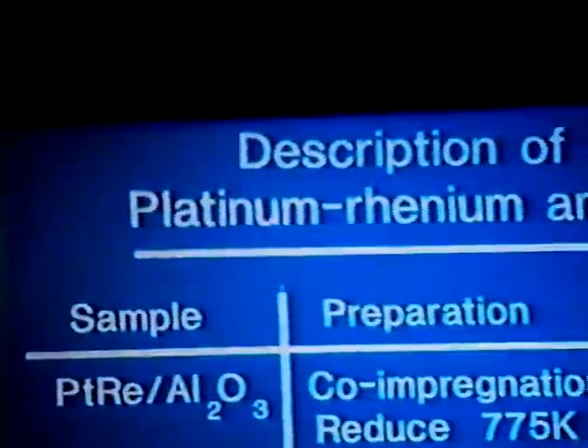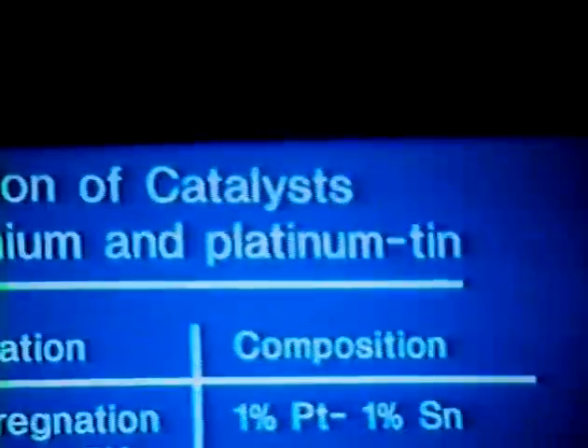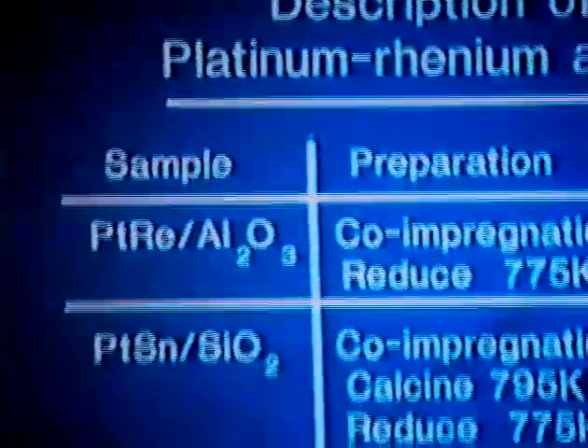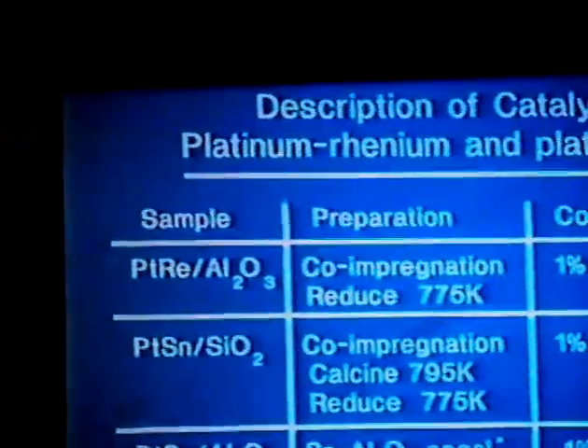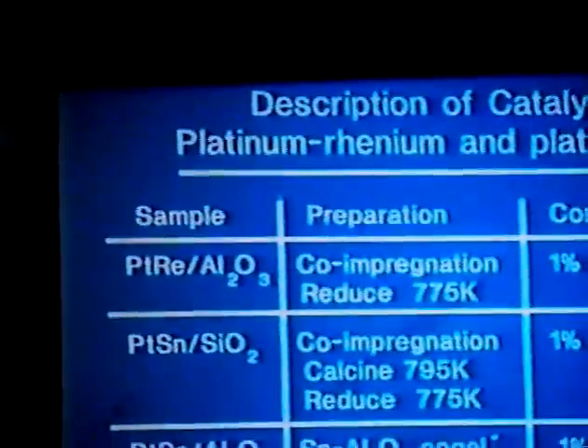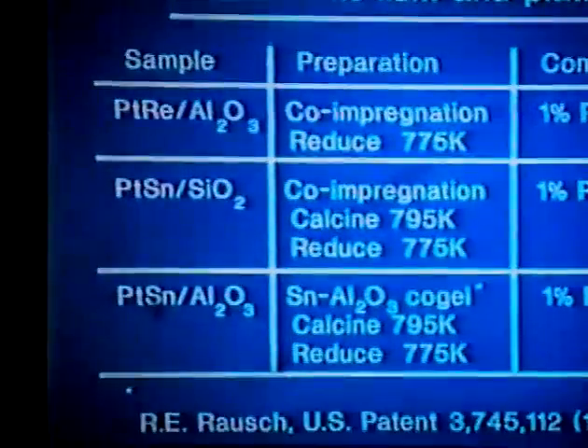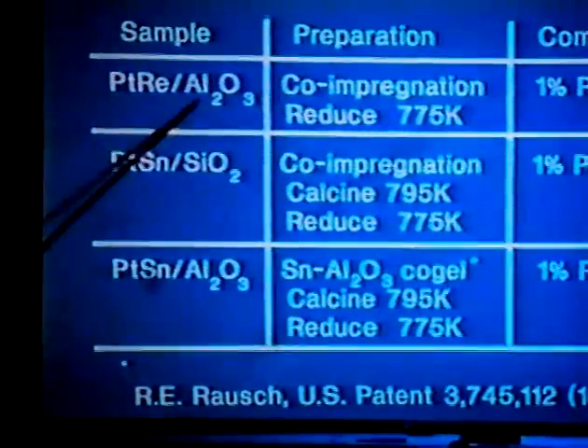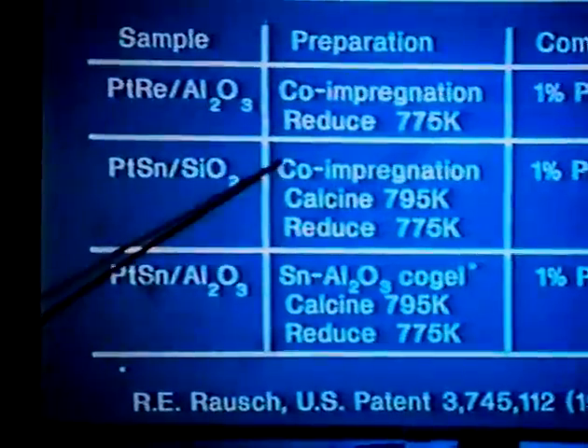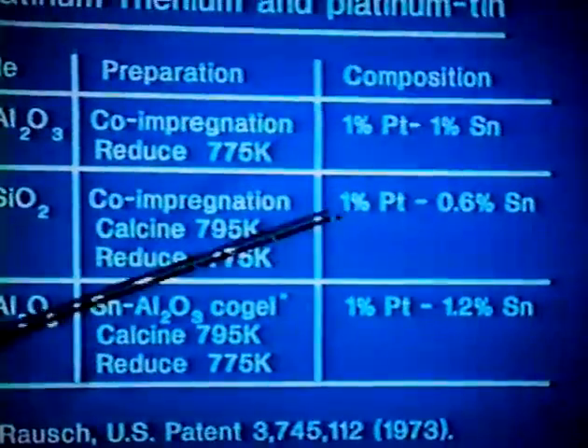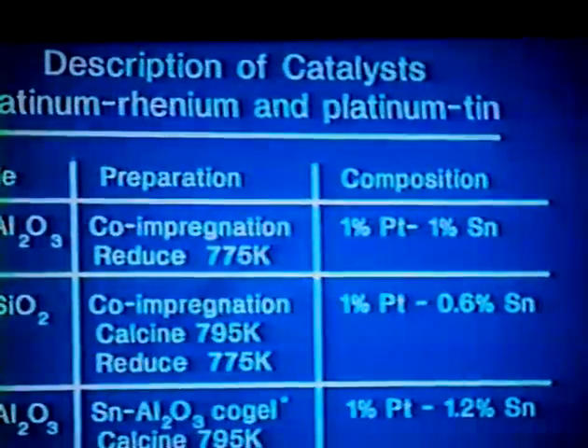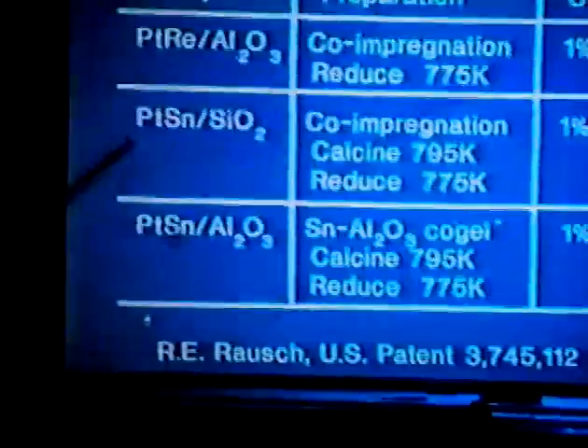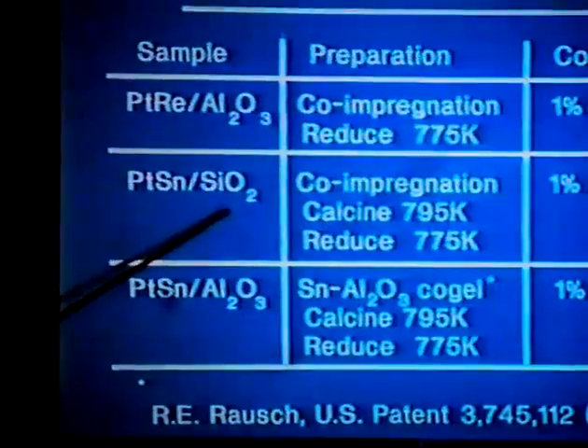And this is a description of the catalysts. Platinum rhenium and platinum tin, both reforming type catalysts. Neither of these, of course, are commercial catalysts. They're not proprietary materials. They're materials we made ourselves, but they do, at least to some extent, simulate the proprietary ones fairly closely. Platinum rhenium on alumina prepared by co-impregnation and reduced at 775 Kelvin. There's a typo here. This is 1% platinum and 1% rhenium, so the atomic ratio is 1 to 1.